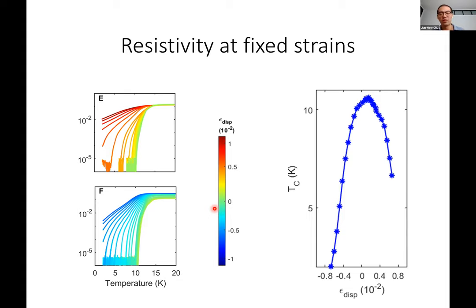So first of all, this is quite a large pressure. And second, I don't think they are exactly the same, because obviously they belong to different symmetry classes. Sure, the symmetry is different, but just empirically, you're saying the effect is quite different with the two kinds of pressures. Well, curiously, the R versus T actually looks quite similar. I suspect it's probably doing somewhat similar things, right? When you apply pressure, it kind of shifts the whole phase diagram towards more underdoped, and therefore you're enhancing the nematicity. I think the effect is very different for optimal doping, which I'm going to show in a few minutes.